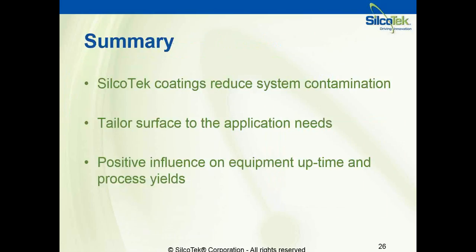So to summarize, SilcoTek coatings will reduce system contamination by preventing reactions between process media and the substrate of the components that make up the system. Eliminating corrosion, eliminating chemical adsorption and reactivity, and preventing the ions from the metal substrate below from leaching in and causing failures is exactly what these coatings are designed to do. We're able to tailor the surface based on the needs of your application, whether that be a non-reactive barrier or simply an amorphous silicon layer that is corrosion resistant and needs to last a long time. We have the capabilities to tailor the coating to your needs.